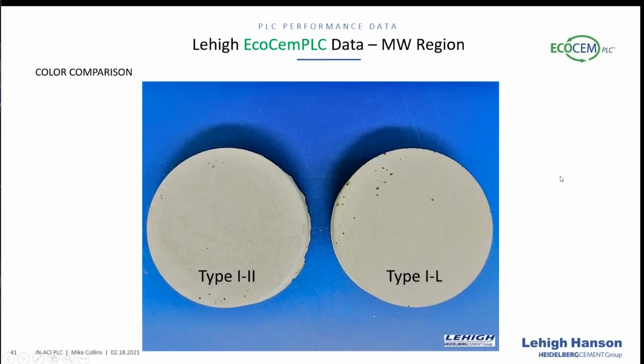Color. You are adding more limestone, right? And limestone is typically much whiter than clinker is. So under glass, if you were to look at the two powders, the PLC would be lighter. If you've ever been to our concrete school, for instance, we show you a Type 1 cement under glass versus a Type 3. From the same plant, the Type 3 will always be lighter, because it has more gypsum in it. So it shouldn't shock us that if we put a Type 1-2 beside a Type 1L from the same plant under glass, that Type 1L is going to be lighter.